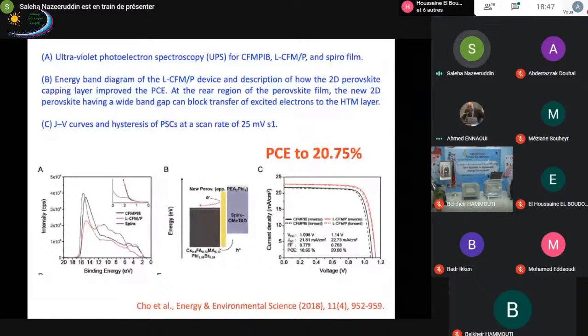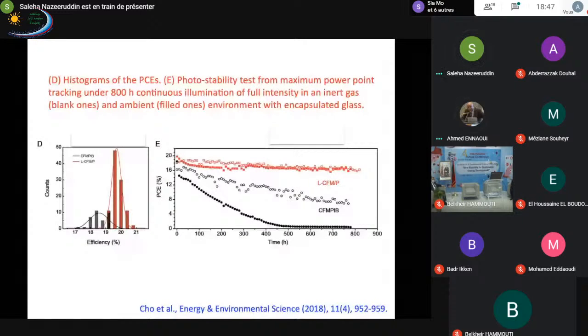Well, the net effect of this, can you see the slide, which is the stability data? Yes. Okay, so the influence of this two-dimensional perovskite is shown here. The black lines, the filled ones, are under atmosphere conditions. The stability is decreasing significantly. This is without any two-dimensional perovskite. And if you look at the black open circles, these are under nitrogen atmosphere conditions, but still the efficiency is decreasing. Nevertheless, the moment we deposit two-dimensional perovskite on top of three-dimensional perovskite, the solid line is under atmosphere conditions, and the empty squares are under nitrogen conditions. The stability is significantly enhanced. So our idea of stabilizing these perovskite materials by incorporating two-dimensional perovskite is a really successful strategy.